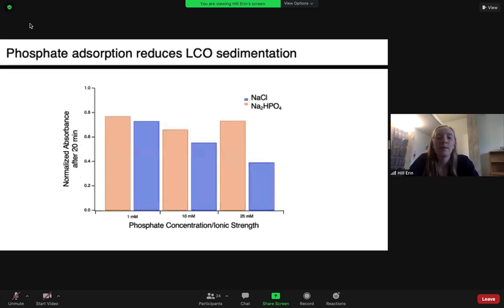To test this, 3 solutions, each of NaCl or Na2HPO4, were prepared at 3 different concentrations. We know that the LCO solution will absorb UV-Vis light because it is colored, and so the absorbance at 350 and 414 nanometers was measured periodically over 20 minutes, and the difference between those 2 measurements is what we see here.